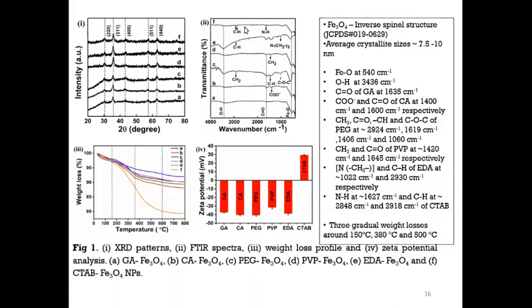So FTIR is one of the techniques to predict that there is surface functionalization. However, this is not the only technique to find the surface functionalization. We can go for the weight loss mechanism, meaning how the nanoparticle surface is coordinating with the ligands. TGA, or thermogravimetry analysis, gives certain information, and you can see that there is a sequential weight loss when we increase the temperature.